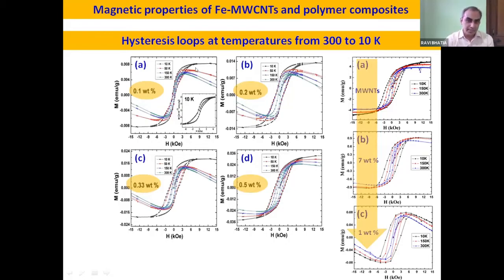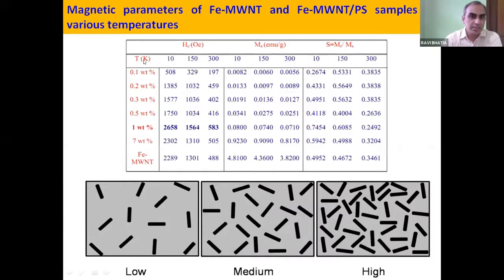And this part, which is after the saturation, is from the diamagnetic contribution from the composite polymer as well as CNT. So this thinning of the loop is interesting, and there is a wavy nature in the case of 0.2 and 0.33 samples. So I will just go to the next slide and first show you the table, which is very interesting. So just look at the temperatures 10, 150, and 300, and the coercivity values.